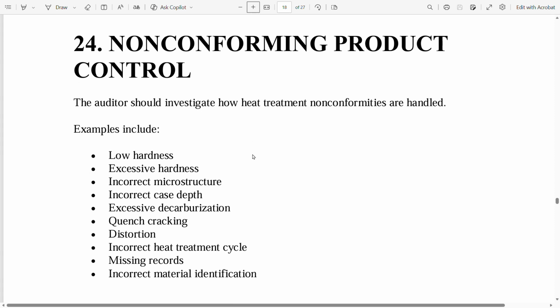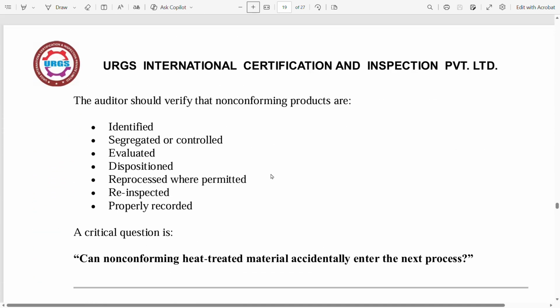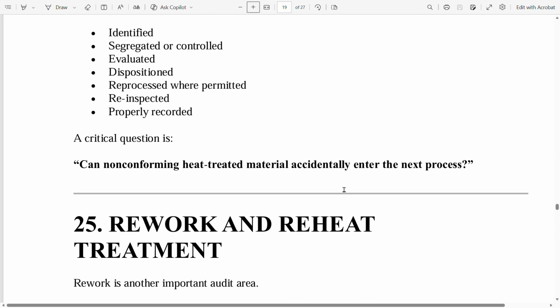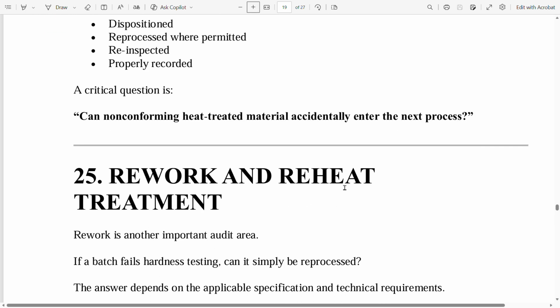24. Non-conforming product control. The auditor should investigate how heat treatment non-conformities are handled. Examples include low hardness, excessive hardness, incorrect microstructure, incorrect case depth, excessive decarburization, quench cracking, distortion, incorrect heat treatment cycle, missing records, incorrect material identification. The auditor should verify that non-conforming products are identified, segregated or controlled, evaluated, dispositioned, reprocessed where permitted, re-inspected, properly recorded. A critical question is, can non-conforming heat-treated material accidentally enter the next process?